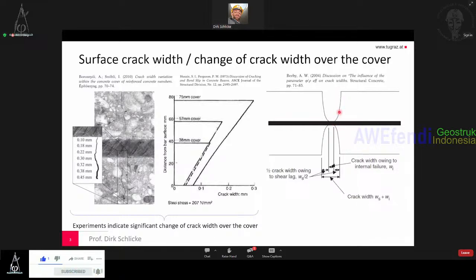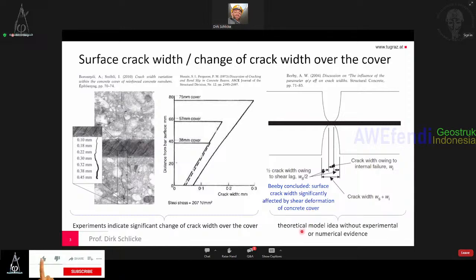And he assigned in this idea one half of the crack width to sort of a slip. He called this internal failure. And the other half of the crack width, he said, comes from the shear lag. So he concluded the surface crack width is significantly affected by shear deformation of the concrete cover. However, behind this theoretical model idea, there is no experimental or numerical evidence. So this was an assumption.